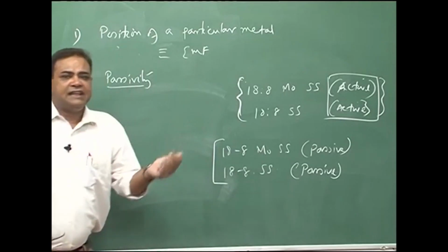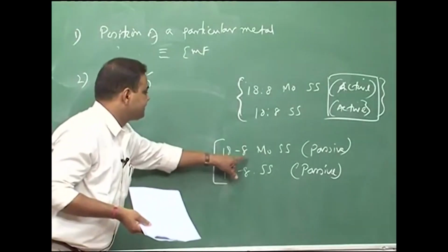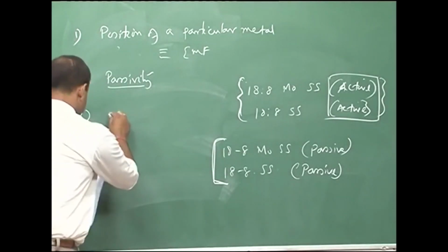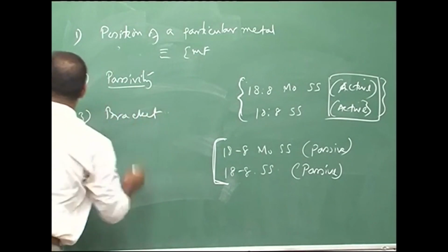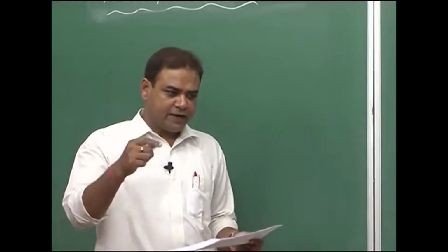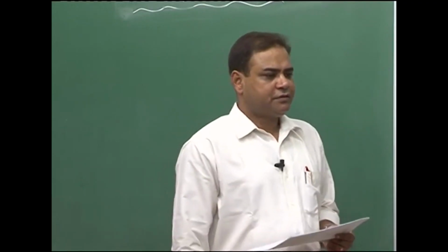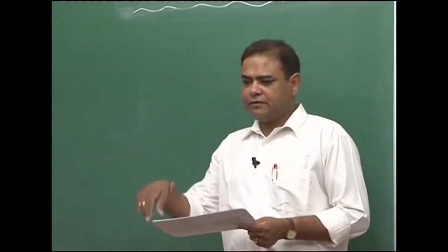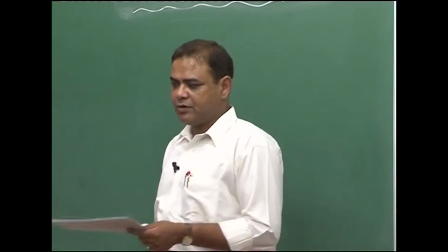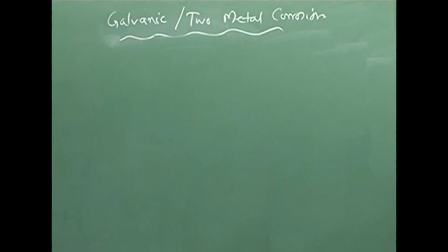So, there would be less galvanic coupling or galvanic effect, and so the corrosion rate would be the same for both the cases. So, that is why they are bracketed. This is the meaning of bracket in the galvanic series. We see that in the galvanic series we have the bracketed regions, and in practical use this has a great implication. Those bracketed metals and alloys can be clubbed together in practical operation without much galvanic corrosion effect. Uniform corrosion would always be better.